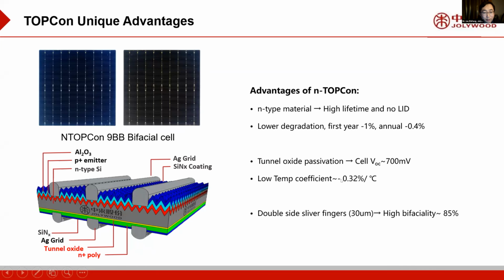The cell open voltage now is about 700 millivolts, and the TOPCon solar cell has a high open voltage and low temperature coefficient. Because on the rear side we use silver fingers, the finger width is just 30 micrometers. So the bifaciality now is about 85% for the solar cell.